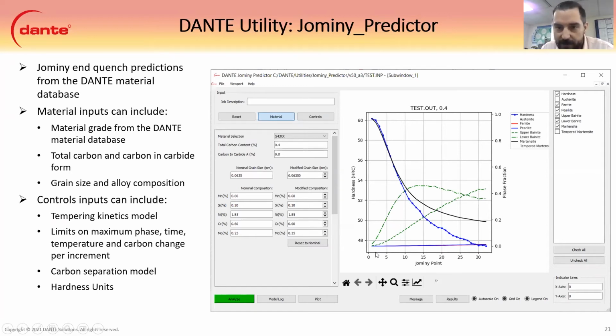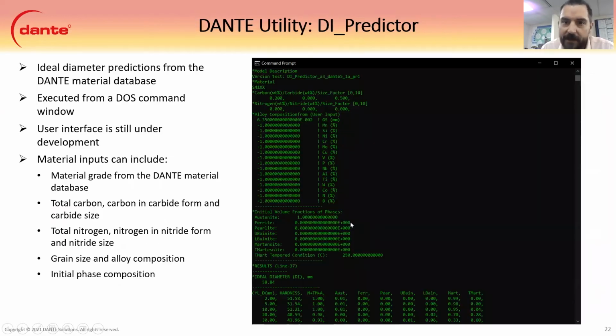And from here, you can see you have some bainites being formed right near the surface. You have a lot of martensite, this black line here. And that tells you how much percentage here. You can see the phase fraction on the right. So at the very surface, we have 100% martensite, and then it goes down. Actually, we have a little bit of bainite too. And then it drops off as the bainite comes into play. And this will help you design. A lot of people use Jominy in design.